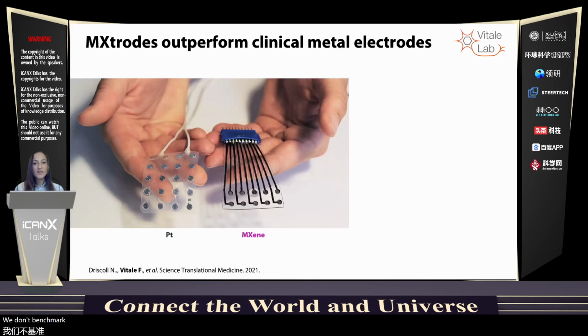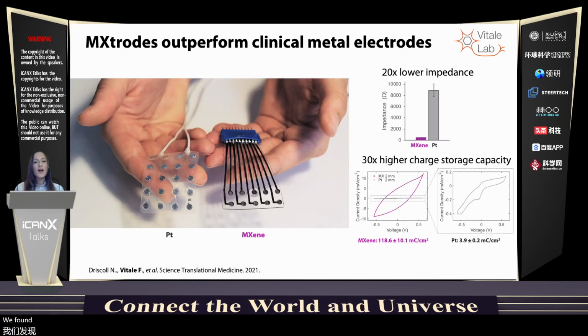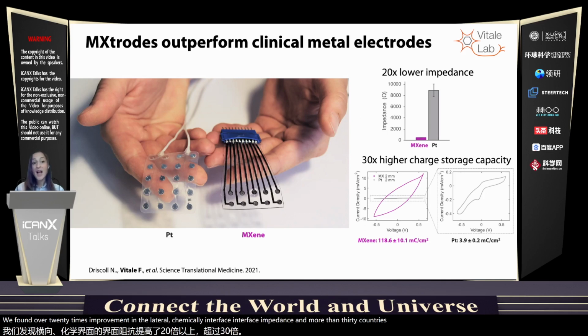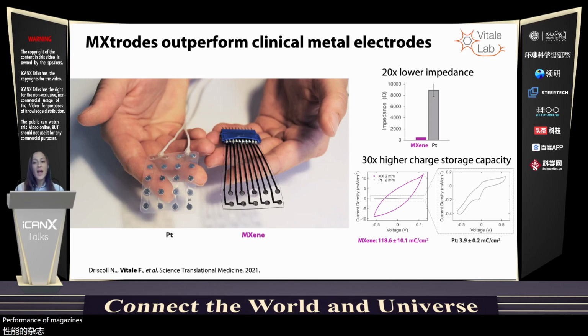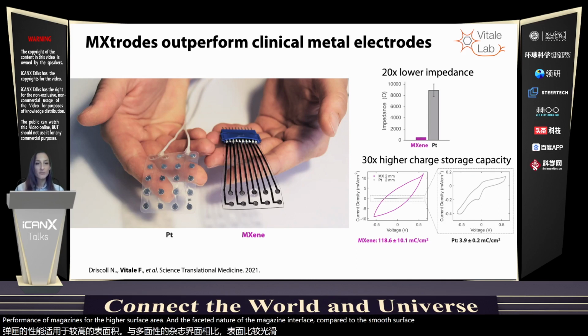We then benchmarked MXene electrodes against commercial clinical electrodes made with platinum and again measured the electrochemical properties that are relevant for recording and stimulation of bioelectric signals. We found over 20 times improvement in the electrochemical interface impedance and more than 30 times higher charge storage capacity for MXtrodes compared to platinum, which implies an improved ability of these devices to store charge and then release it for safe and effective electrical stimulation. Again, we attributed this enhanced electrochemical performance of MXenes to the higher surface area and the capacitive nature of the MXene interface compared to the smooth surface of platinum.